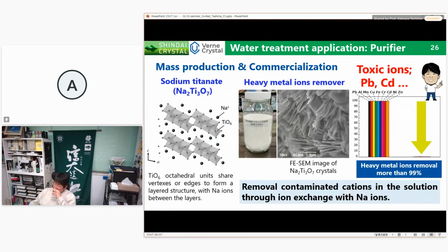In our laboratory, we have developed sodium titanate crystals that selectively adsorb heavy metal ions. The use of these crystals has made it possible to easily remove harmful heavy metal ions dissolved in water. The mechanism of ion adsorption is an ion exchange system.